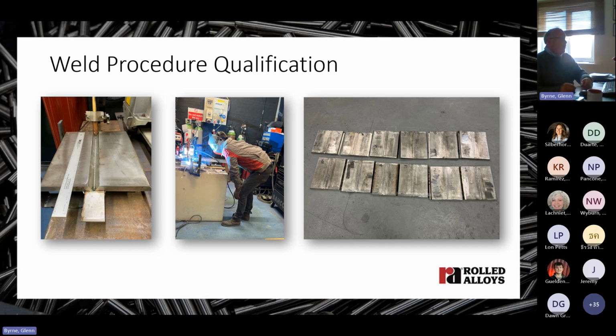We find that sigma phase formed by the fastest weld thermal cycles is not as detrimental as sigma phase formed isothermally in a furnace. Its size, shape and composition are not the same. So welds with small quantities of sigma phase can pass toughness and corrosion test requirements. Unlike for raw products, when applying the microstructure check as part of a weld procedure qualification, we've been inclined to accept some visual evidence of sigma in the microstructure, provided the corrosion resistance and toughness testing passed and the microstructure of these samples was the same as that seen in the original microstructure check sample. And this is the position adopted in the ISO 17781 standard.